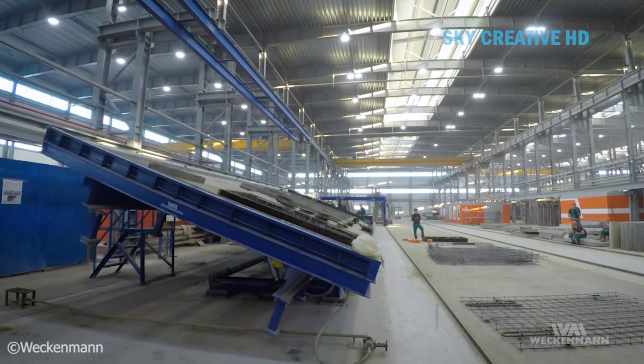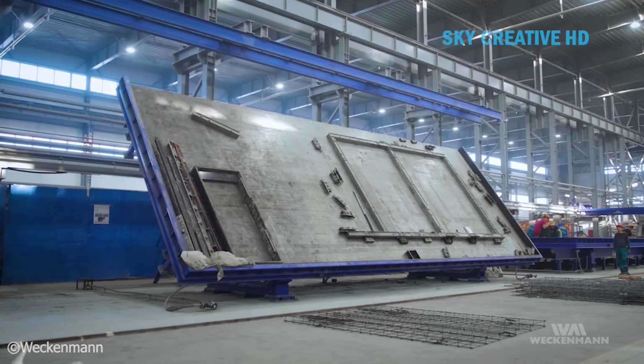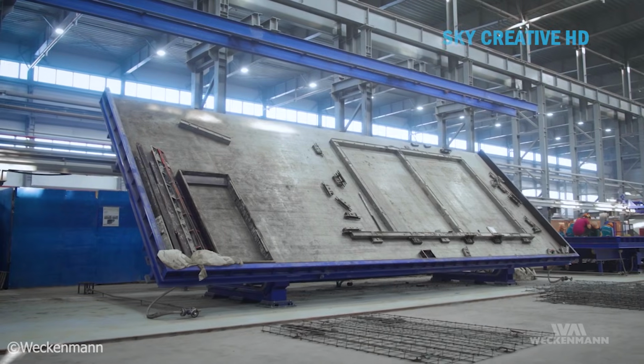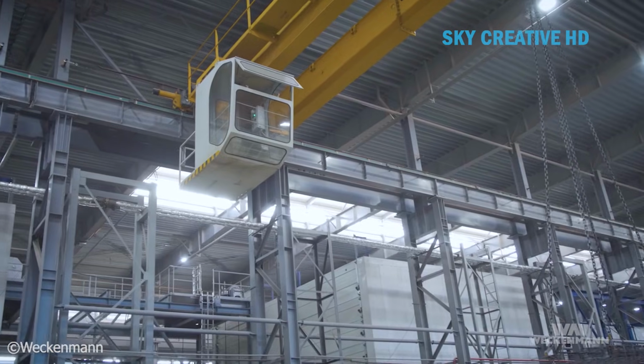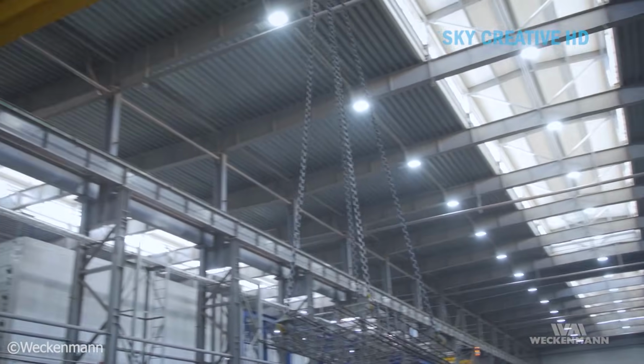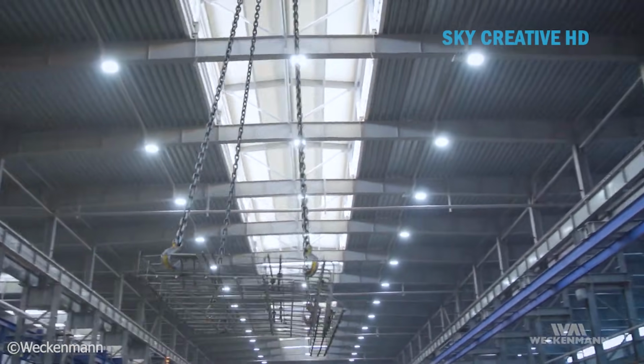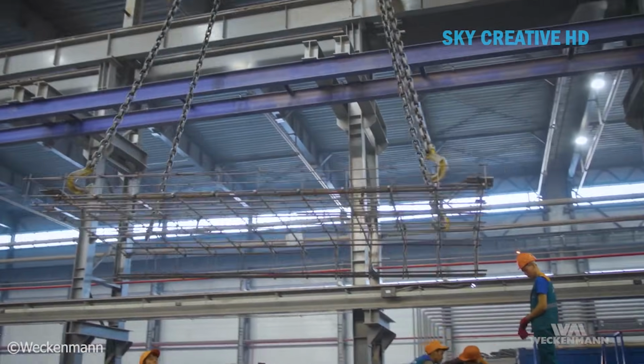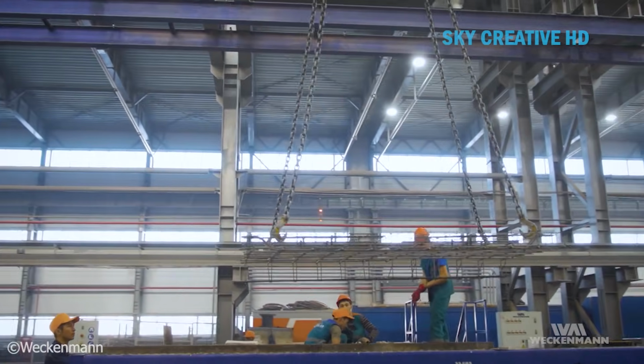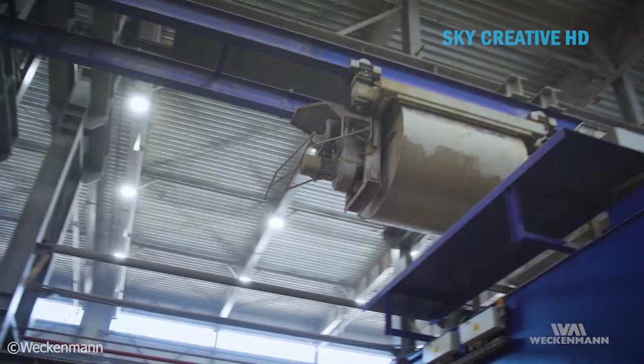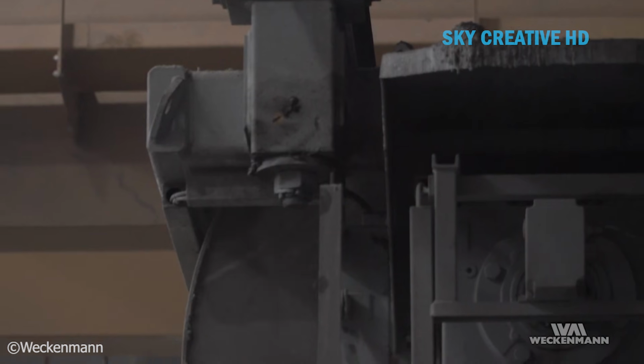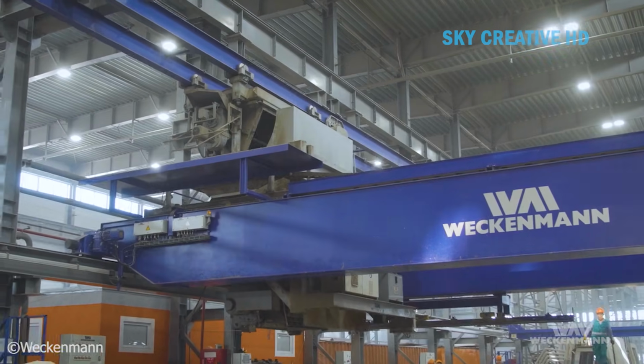Many precast elements require steam curing to accelerate strength development. Weckenmann designs curing chambers where temperature and humidity are precisely controlled. The elements are gradually heated to around 150 degrees Fahrenheit and held there for several hours. This accelerated curing allows pieces to be demolded and handled in less than a day, compared to the week or more required for conventionally cured concrete.